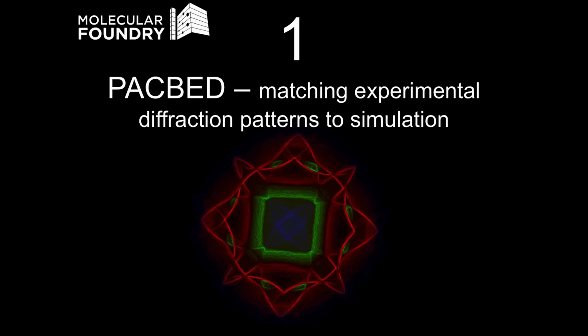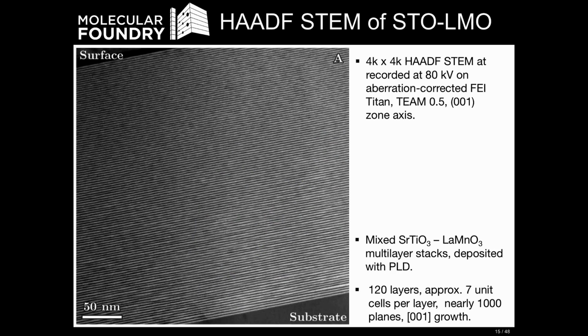That stands for position averaged convergent beam electron diffraction. And this is the simplest possible way to use the data. We're going to match our experimental diffraction patterns directly to simulation. So first, what does a conventional image look like? This is a multi-layer stack material. It alternates between layers of strontium titanate and a mixture of strontium titanate and lanthanum manganate, and it was deposited with pulsed laser deposition. Each one of these layers is about 7 unit cells, and there's 120 of them, so almost 1,000 planes here.